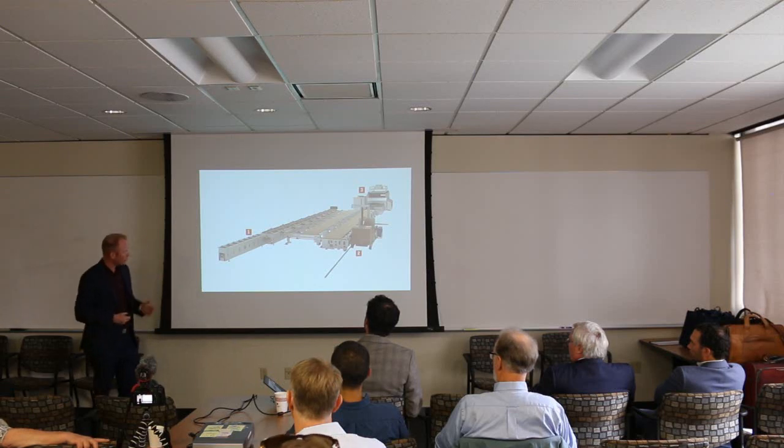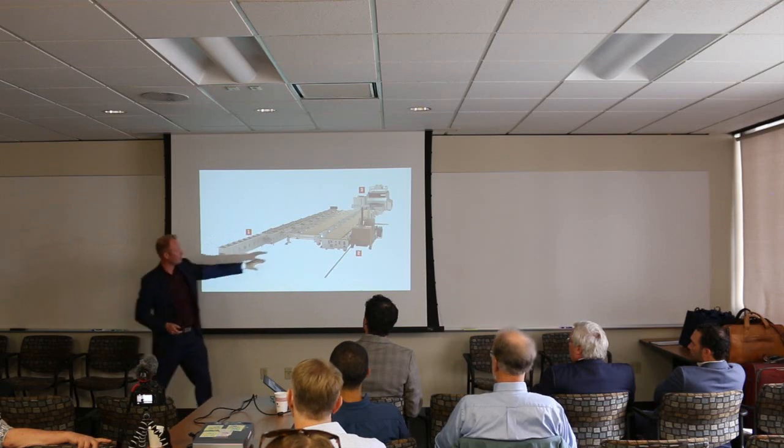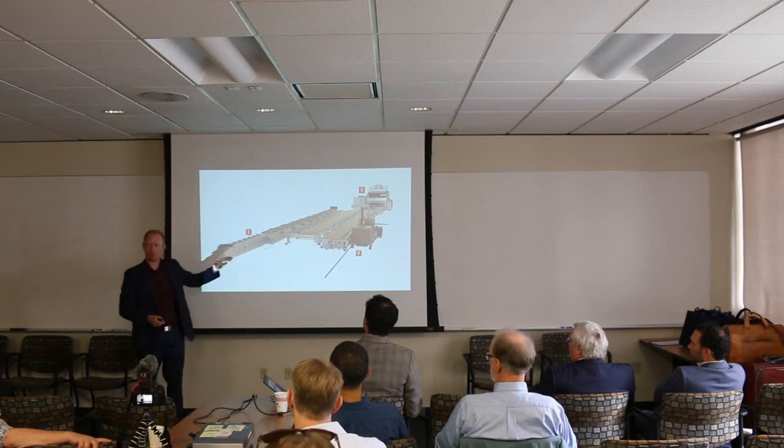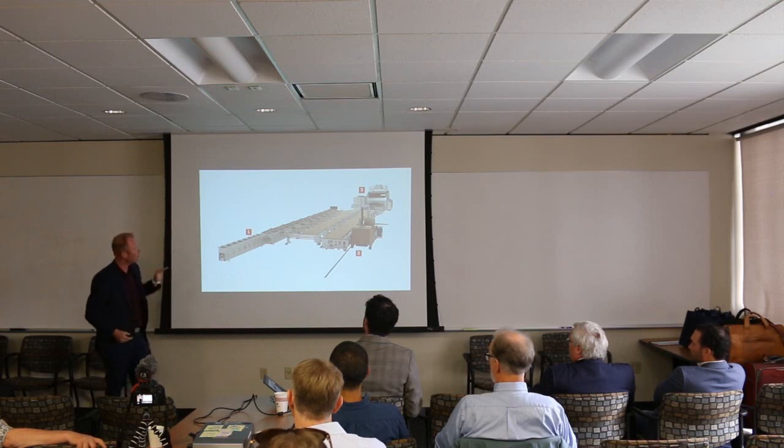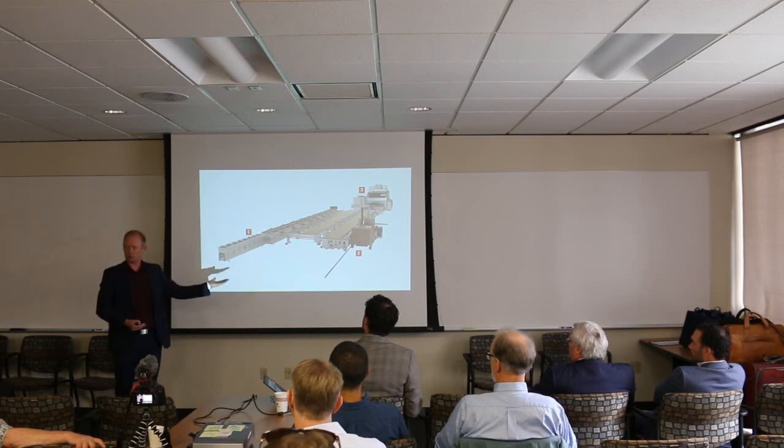What does that mean? This shows you right here, it's what they call the combi press. So you can see the layers, they've already been finger jointed, they're going on here. Now you have to envision in this space here, there's going to be a layup line that's going to put the cross lamellas in, the shorter pieces that are going to go in there. That will have a layer of adhesive, it'll automatically place the short lamellas on there, and then it will put the other layer on top, and you could do 3, 5, 7 plies, goes through that system.